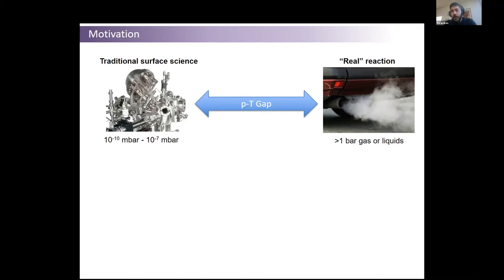Now, there are two problems. The first problem is thermodynamics. In traditional surface science studies, we are actually probing the surface at a different point in the thermodynamic phase diagram. So when we probe the surface in the presence of gases, there's going to be an equilibrium shift. And the second problem is that because of our choice of pressure and temperature, the chemical potential is virtually 0 electron volts. So if there are some kinetic barriers, we will not be able to overcome them.